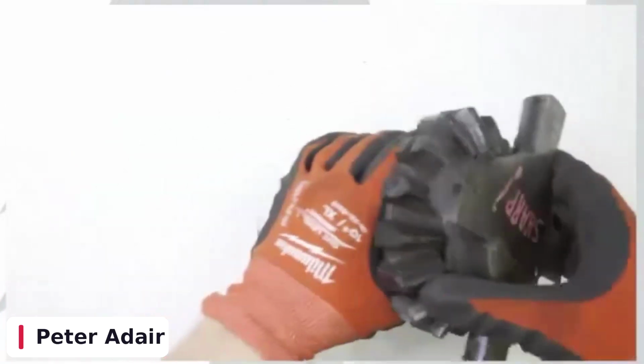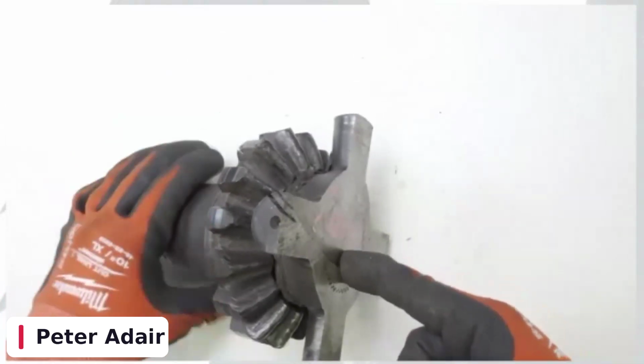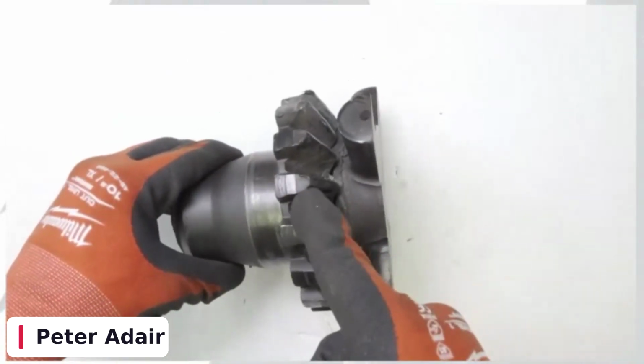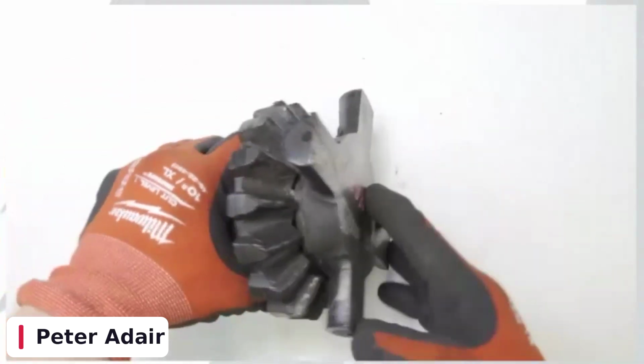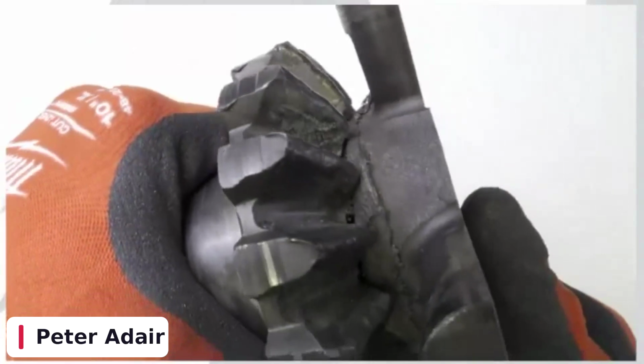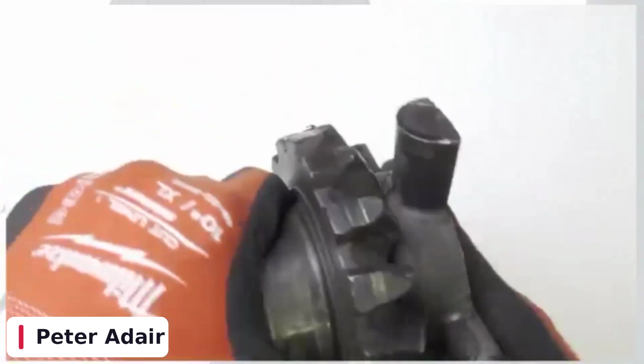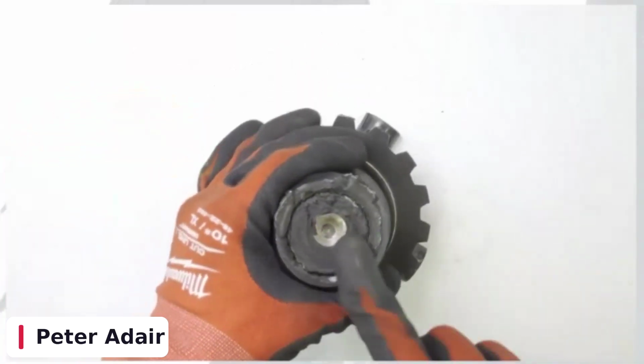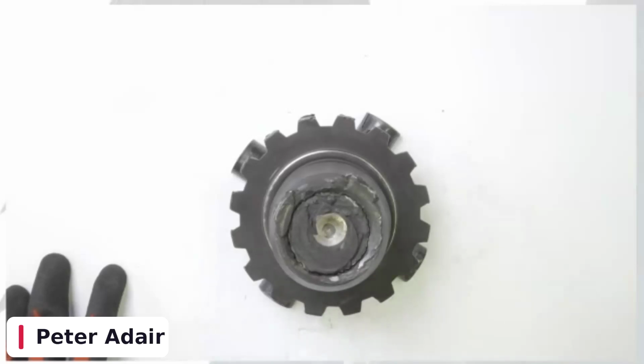So like I said, spin out is our number one failure point. And it comes down to drivers knowing how to use their stuff. So in this instance, we have the input shaft welded to the rear side gear. This system got so hot, we literally melted and rolled steel. And then it got hot enough to where it detempered the heat treat on the output shaft and the output shaft snapped off.